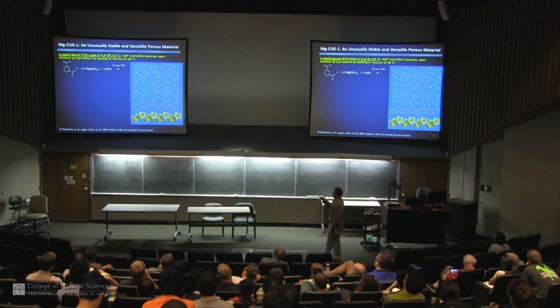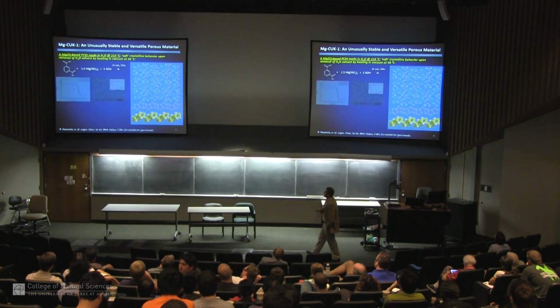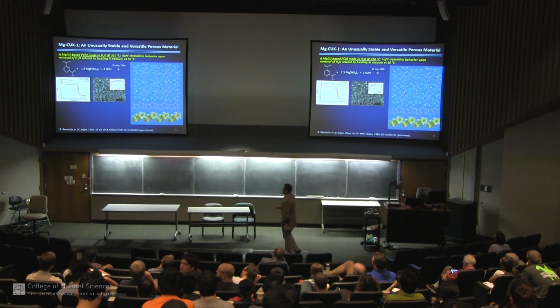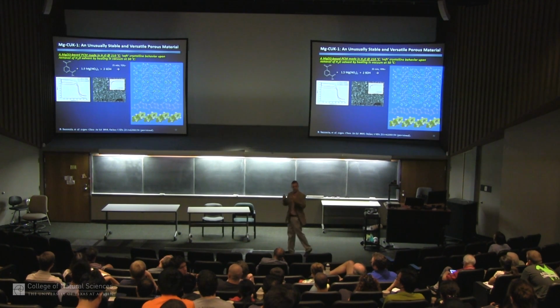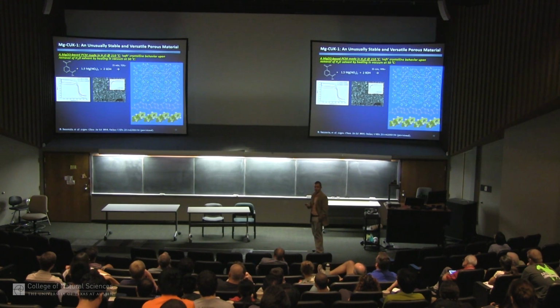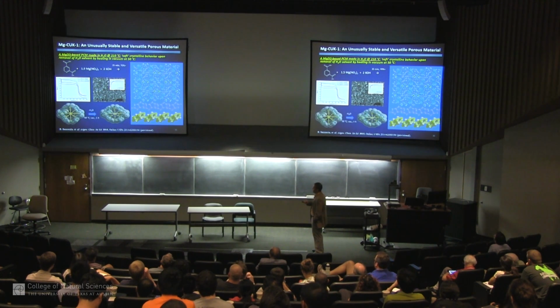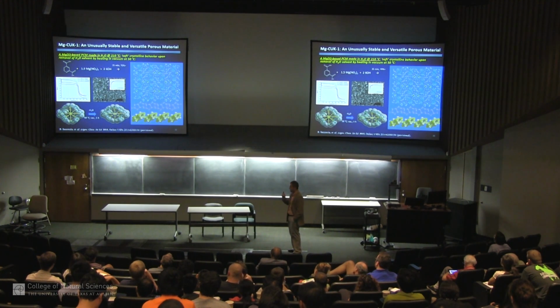By crystallography, you can see all these yellow atoms are just water. They're filling these square pores. But this material has some very unusual properties. It's thermally stable, and this is a TGA trace, up to 500 degrees because the metal ligand bonds are very strong. This is what the SEM of the crystal looks like. If you make crystals in 30 minutes in the microwave, they're always small, so you have to pay attention to that. But we can take these crystals again and heat them up on the diffractometer and see single crystal conversions,